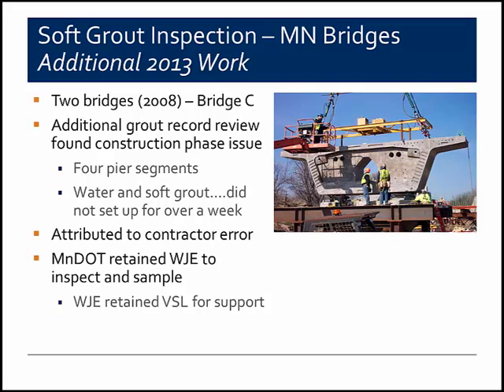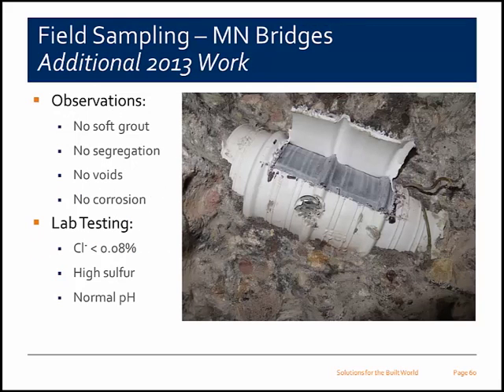But as a result of some of the issues that have come to light, MnDOT wanted to go back out and take some samples just to confirm that there was no soft grout present in these tendons where the issues had been noted back in 2008. And so WJE was again fortunate enough to be asked to go out and collect those samples and take a look. And similar to before, what we found was no problems, no corrosion, no soft grout issues, no voids.